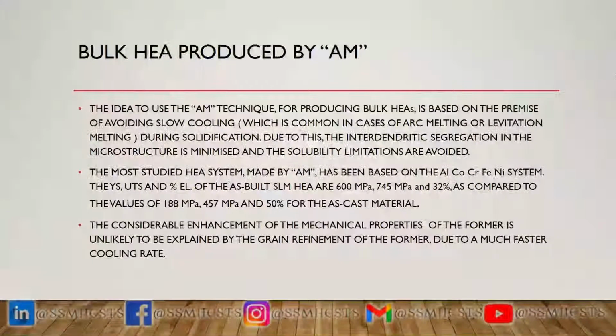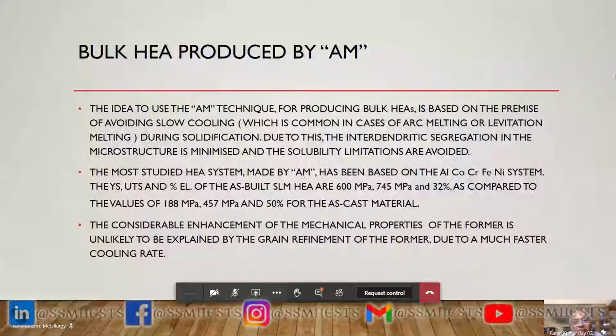So the considerable enhancement of the mechanical properties of the AM product is unlikely to be explained by the grain refinement of the former due to a much faster cooling. A lot of people try to give an account for the exceptional strength by looking at the finer grain size, but they couldn't explain it. So there are things other than fine grain size which must be considered. The next one, please.